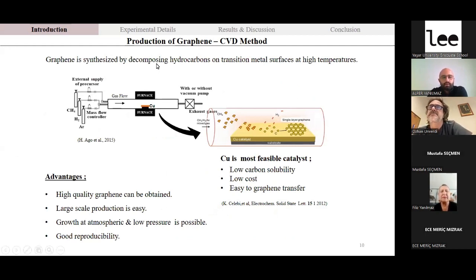Actually, to continue with the production methods, in our study we use the chemical vapor deposition method. This method is related to decomposing hydrocarbons on a transition metal surface at high temperatures. By the way, graphene is synthesized this way, and different transition metals can be used, but the well-known and most feasible catalyst is copper, due to the low carbon solubility, low cost, and it is very easy to transfer graphene to another desired substrate with this transition metal.